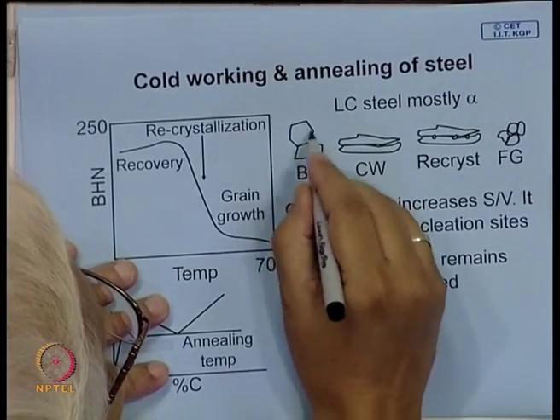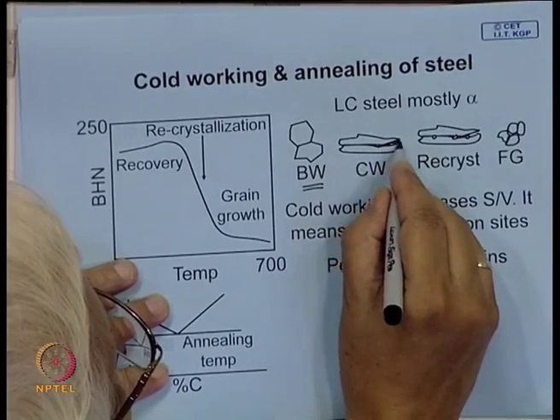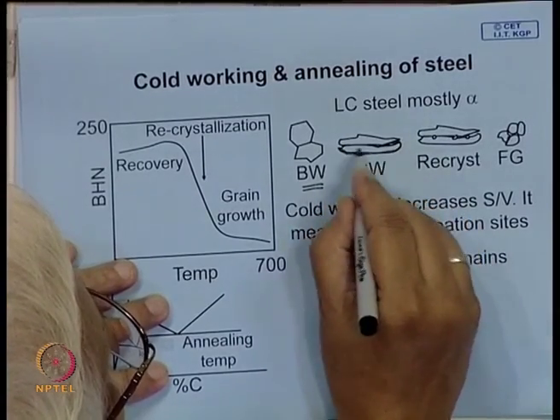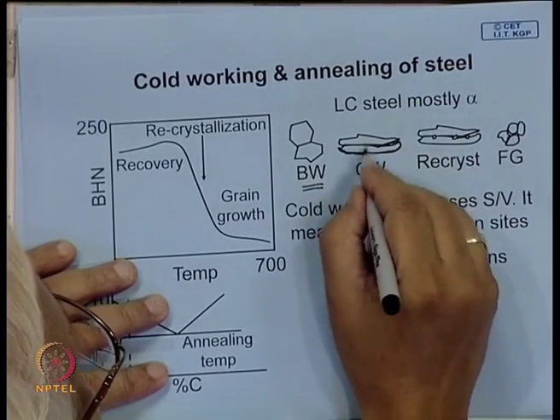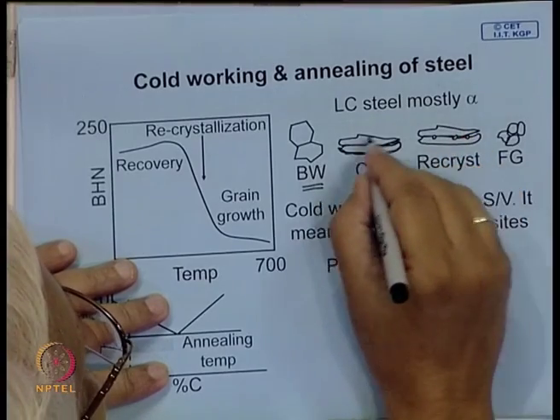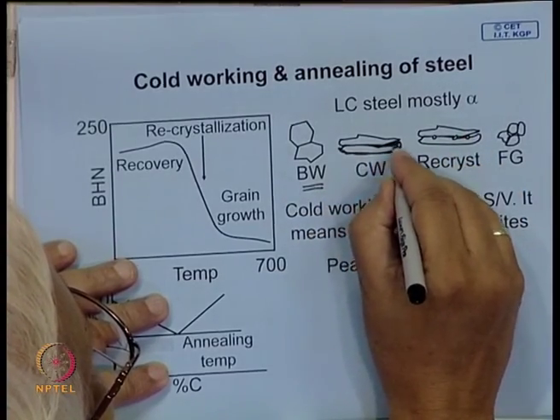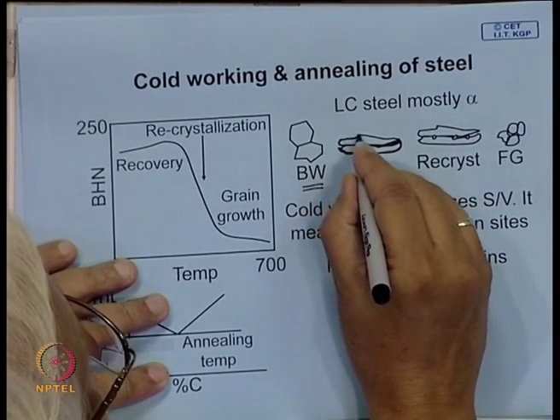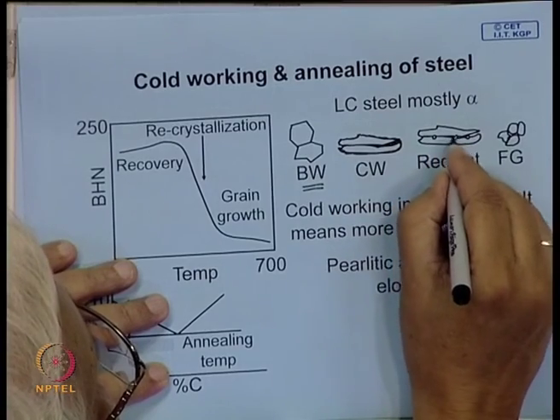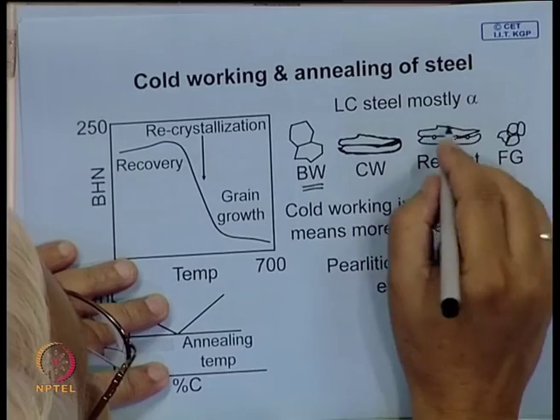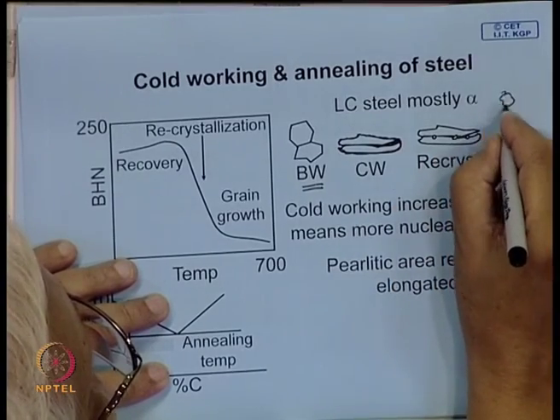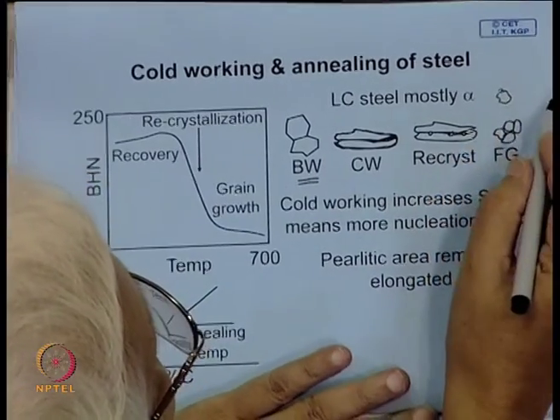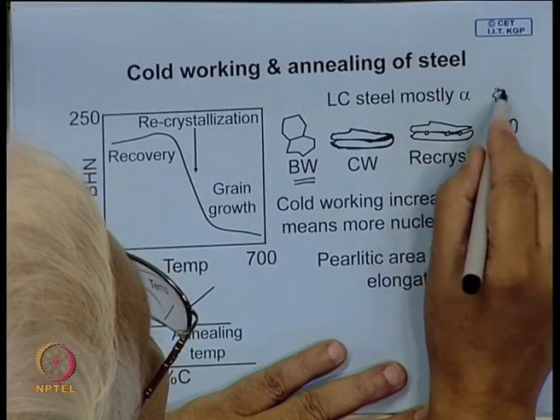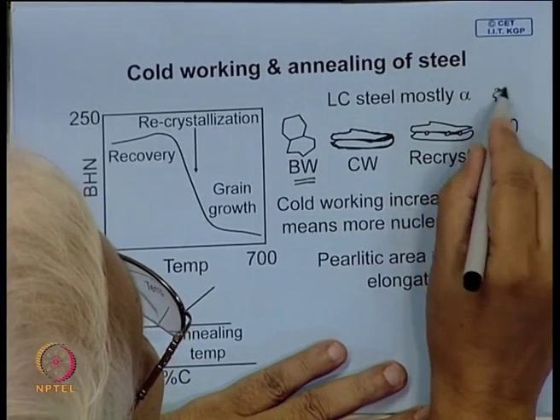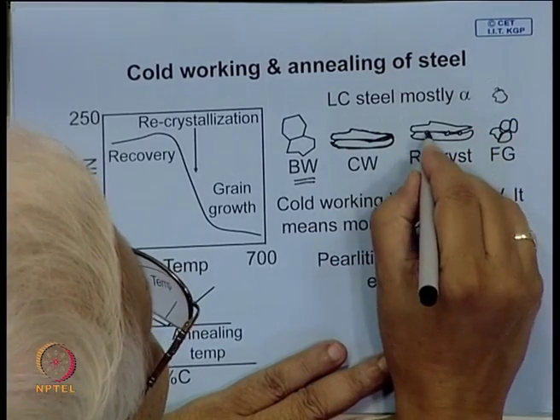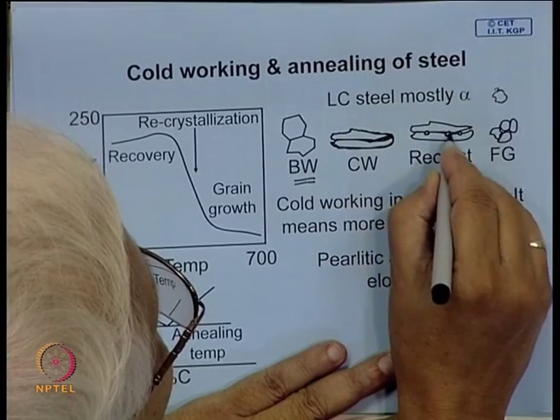These are the grains before working, and when you cold work, the grains get elongated and you have a large grain boundary area. When you heat during annealing, the material has a high stored elastic energy, and it will try to come to a position of lower energy. So there is a driving force existing, but a fresh grain cannot nucleate easily, because to nucleate a new grain, new surface area has to be created. One has to overcome that surface energy barrier, and grain boundaries provide such heterogeneous locations where it can easily be overcome.